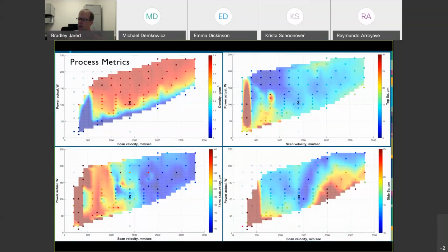Looking at the vertical axis is the laser power, the horizontal axis is the scan velocity, and the circles are all areas where we ran parts. The open circles are parts that failed in this space, and the closed circles are parts where we were actually able to print cubes. You'll see in some spaces we have some surface finish data, which is related to the fact that we built a little bit, but not enough for, say, a density measurement. You'll see a range, high density is up here at the top, but if you look at the other metrics around surface finish on the top or on the side, or even form, so this would be, say, the waviness or the flatness of the top surface, just because I get good density doesn't mean I necessarily get good surface finish, right?